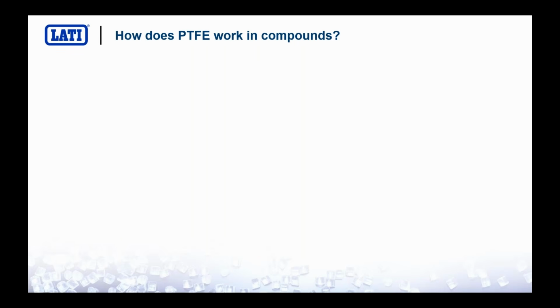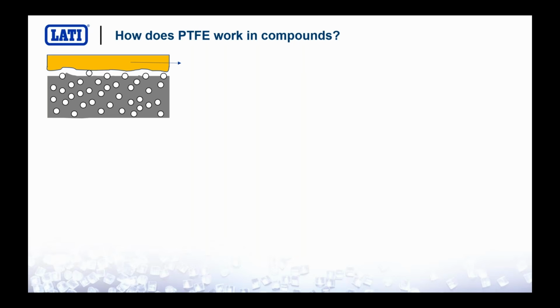But what is the mechanism at the basis of the outstanding tribological performances? Just imagine to have a compound, so a base resin, the gray material, with the PTFE, the white bubbles, dispersed inside the matrix, and the relative movement against a metal, for example, the part in orange. The first step is a burnishing step. So any kind of surface is not flat. They have peaks and they have valleys.